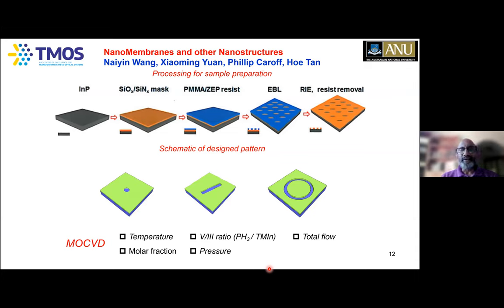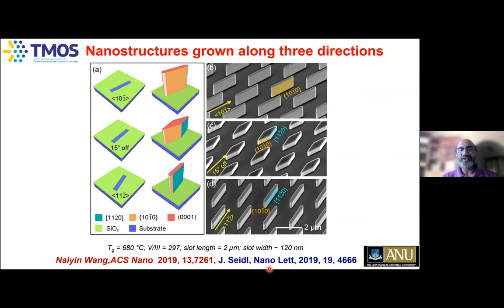So here's a case when you open this slot along this particular crystallographic orientation, 101 bar, put this in the MOCVD reactor, heat it up to somewhere between 620 to 750 degrees Celsius, and introduce the gases needed for the growth of indium phosphide. You can see now you can get these beautiful nanomembranes with these particular sidewall facets. We open this slot along every crystallographic orientation, which is shown here. And again, you do the same thing. You also get membranes, but these membranes have a different sidewall facet than these ones. Also, these membranes are thicker than these ones because lateral growth is taking place in this case.